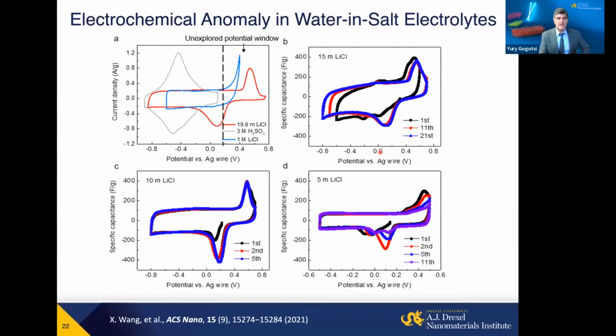One way of doing it is using so-called water-in-salt electrolyte. For example, highly concentrated, close to 20 molar lithium chloride electrolyte. And what you will see will happen. In this case, we can widen the voltage window from 1 volt for sulfuric acid, this is a curve I showed you before here, to about 1.6 volt, which significantly increases the total amount of energy stored, if we can have also sufficiently large capacitance or current density in this case.